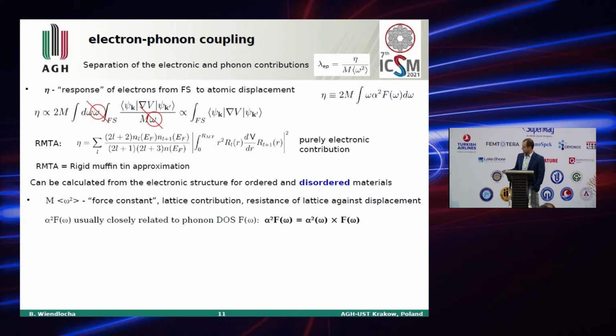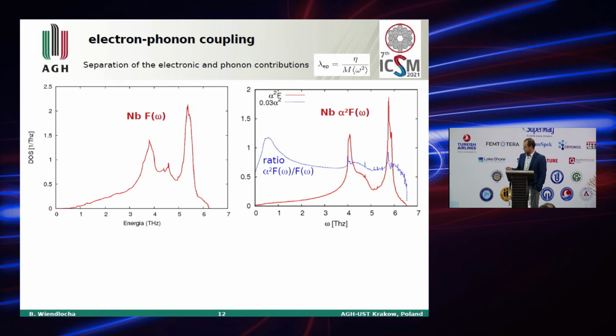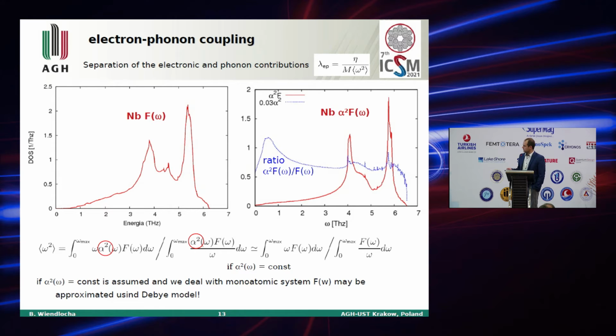And because the Eliashberg function is closely related to the phonon density of states, we may even write the Eliashberg function as a phonon density of states multiplied by a parameter. And if you take a look at the phonon density of states and the Eliashberg function of niobium, you can see that they are very similar, and the ratio of these two, which defines this alpha parameter, doesn't change rapidly. So in such a case, when this alpha parameter is approximately constant, you can calculate this omega square basically from the phonon density of states.